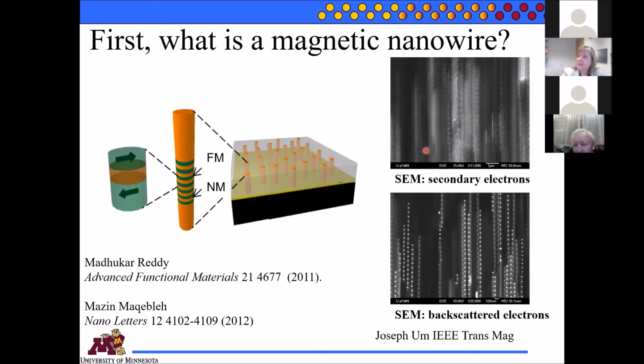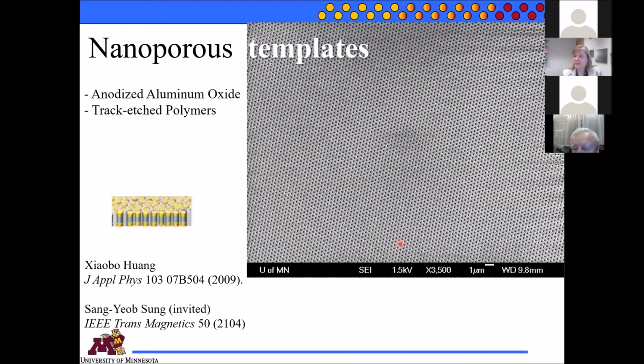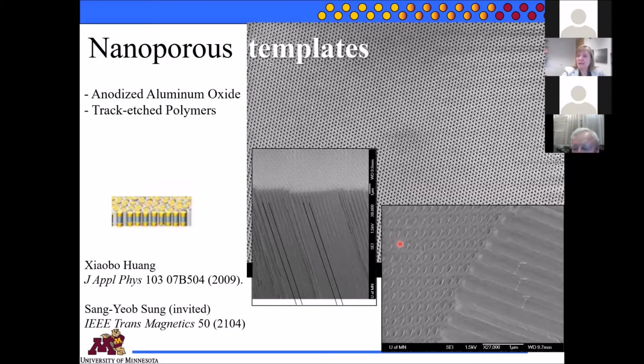Yeah, so here this is just looking at secondary electrons versus backscattered electrons of a fracture surface. So we have our template, we break it and look at the edge. And this is what the templates look like. Anodic aluminum oxide, we have made several very uniform templates in our lab. This is just showing you the length. They're very uniform along the entire length, unless you play some tricks as you anodize to modulate that length, but we haven't needed to do it for this application yet.